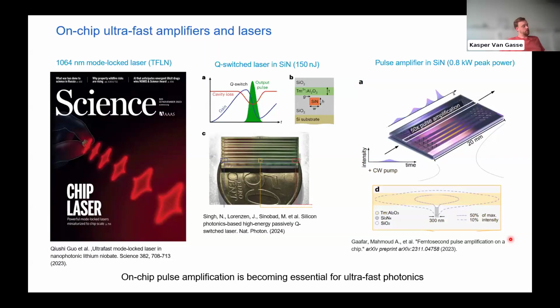But very importantly, in recent years, the development of ultra-fast optics on chip has become quite important. So for example, this is the cover of Science from 2023, where people showed that they made this tiny mode-locked laser at 1064 nanometer using thin film lithium niobate and an LNOI. This was a very nice result, but because it was an LNOI, the pulses were still pretty low energy, long in time, and still not really where we need it for ultra-fast optics on chip. That's really because of this gain material. The LNOI is still not what it needs to be.